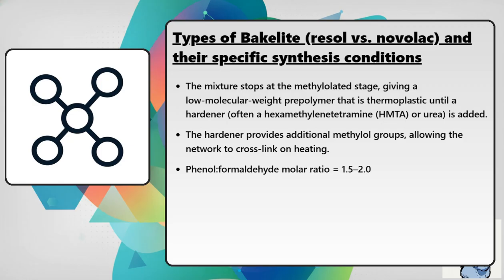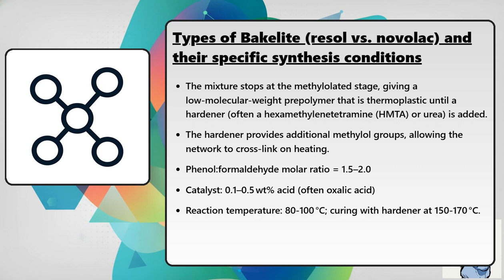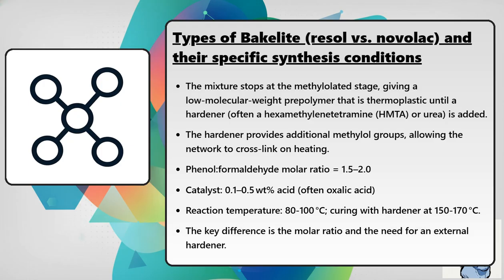Phenol to formaldehyde molar ratio equals 1.5 to 2.0. Catalyst 0.1 to 0.5 weight % acid, often oxalic acid. Reaction temperature 80 to 100 degrees Celsius, curing with hardener at 150 to 170 degrees Celsius. The key difference is the molar ratio and the need for an external hardener.